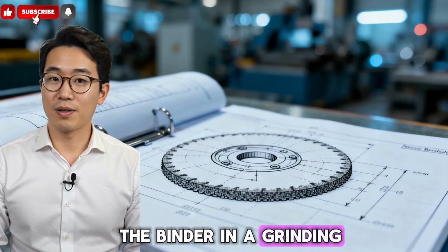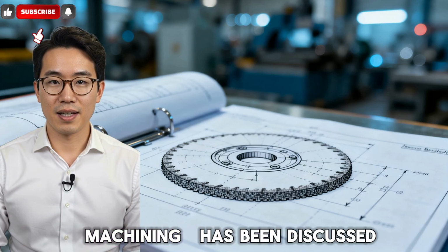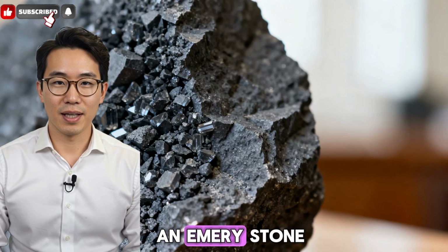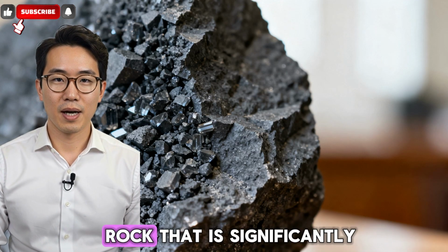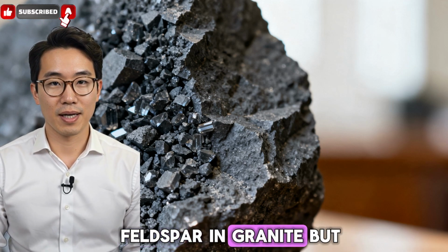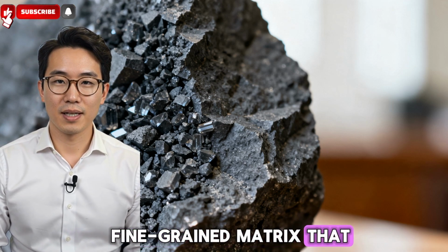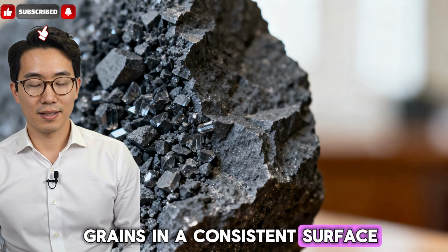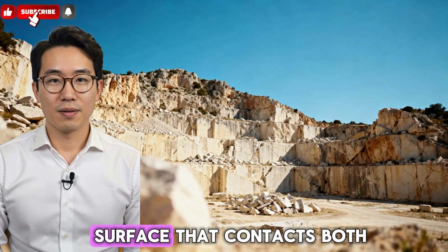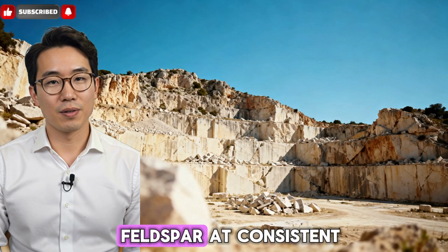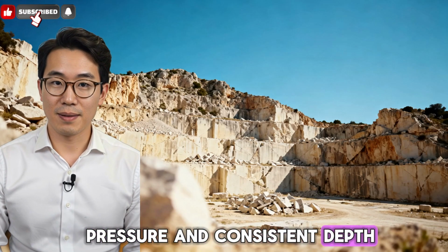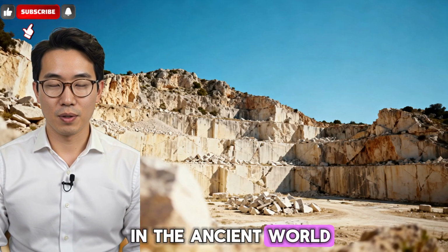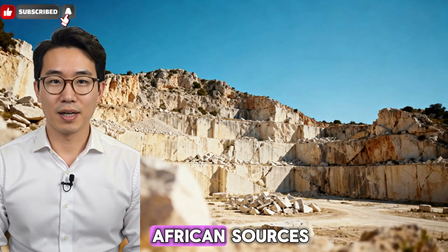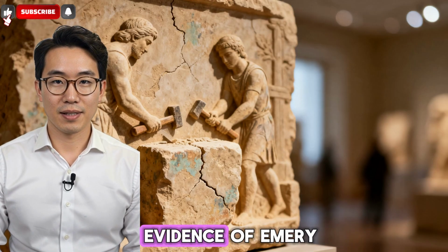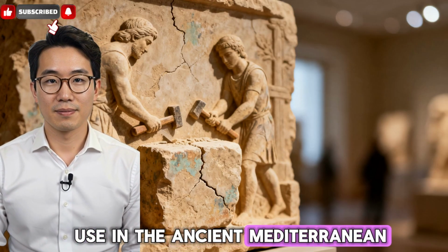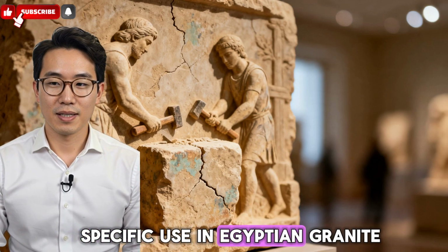the way the binder in a grinding wheel holds abrasive grains in modern machining, has been discussed in the technical literature. An emery stone, for example, a corundum-bearing rock that is significantly harder than the feldspar and granite, but composed of a fine-grained matrix that holds the corundum grains in a consistent surface, could theoretically produce a grinding surface that contacts both quartz and feldspar at consistent pressure and consistent depth. Emery was available in the ancient world from deposits in the Aegean and from several African sources, and there is documentary evidence of emery use in the ancient Mediterranean, though direct evidence of its specific use in Egyptian granite working is limited.